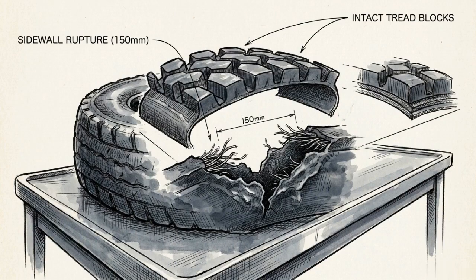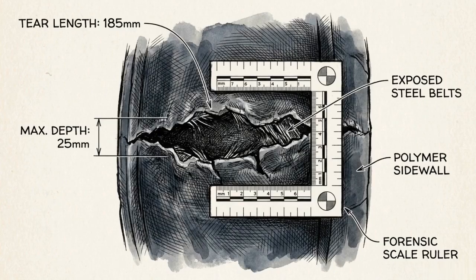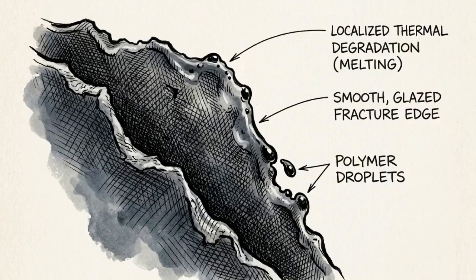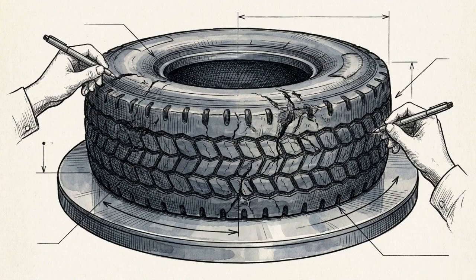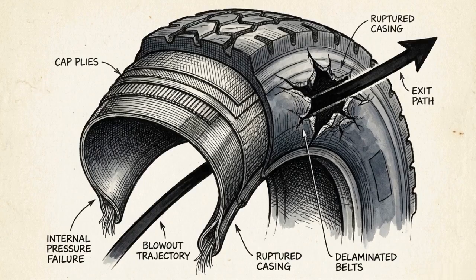In the forensic lab, the ruined casing shows no evidence of general wear, as the tread remains partially intact. The exterior inspection yields two severe anomalies: a massive 150-millimeter crack along the sidewall and distinct visual evidence of localized rubber melting and glazing around the rupture site. Crucially, an exhaustive inspection of the rubber surface reveals zero evidence of a puncture object, cut, or external penetration. The casing was breached from the inside out.